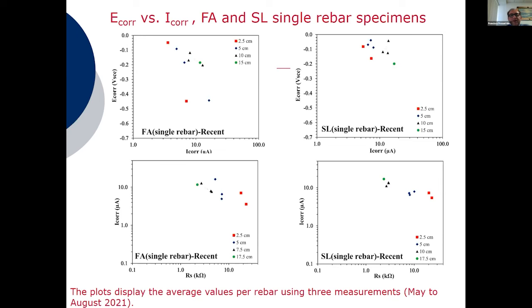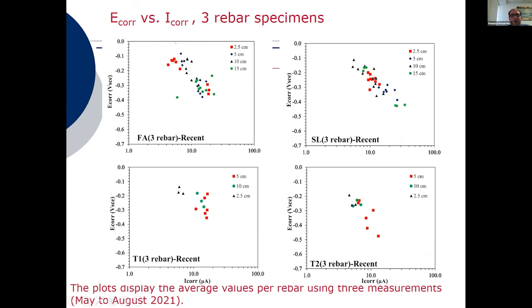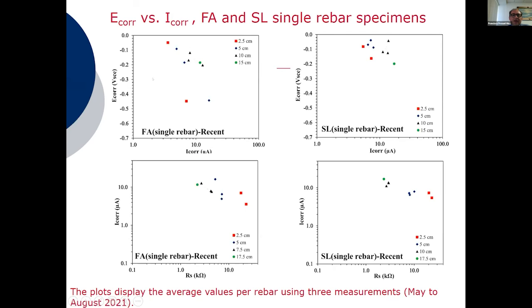And these are for the 3 rebar specimens, and this is the correlation that we observe for the single rebar specimens. In this case, on the top, I'm showing you for the FA, the corrosion potential versus the corrosion current. And you can see compared to the previous plot here, that it is shifted to the left a little bit. So the slope is different. And that might be an artifact of the RS and also maybe the amount of ampere-hours that was applied to each specimen.